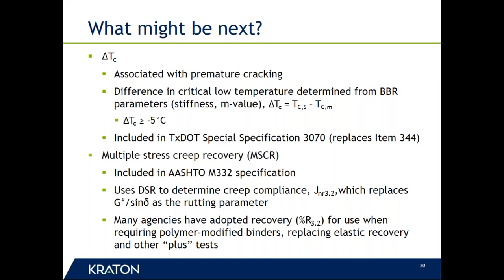The Delta TC criterion is something that now exists in one of the TxDOT mix specifications, which is noted here on the slide. And what this is doing is it's looking at a parameter on the low temperature side to see which is controlling the most, and that is the stiffness of the binder or the relaxation of the stiffness of that binder as it's being loaded at low temperatures.